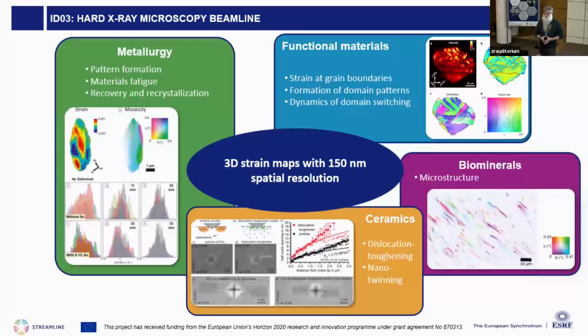The second large group is functional materials, especially ferroelectrics, where we can see the ferroelectric domains, and we can see how these ferroelectric domains are modified by the application of an electric field, by heating or cooling. And we can not only see the arrangement of the domains, which you can sometimes see with polarized light microscopy, but we can also see the strain patterns and the strain distributions within these domains. We have had some first experiments with biominerals where we had problems with intensity. We hope that with the new beamline, we will have much more intensity, so we should be able to also look at more biominerals. And we've looked at ceramics.